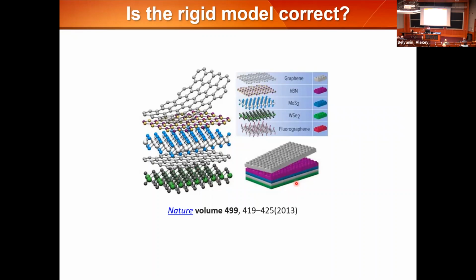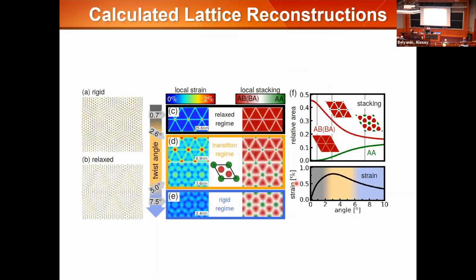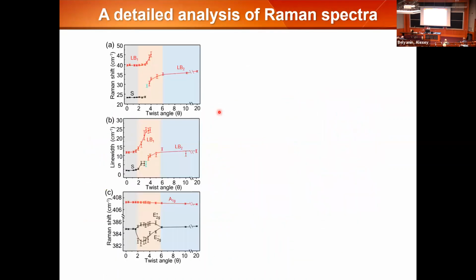And the lattice changes. We now realize that with bilayers, they actually form this triangular potential where within the triangle you have a perfect atomic alignment, and the different stacking only happens on the boundary of these triangles. So that would potentially completely rewrite the selection rule I was telling you about. But this kind of lattice reconstruction mostly happens in what we call the homobilayer, meaning we start with a monolayer and then construct the bilayer using the same material. So I won't elaborate on that.